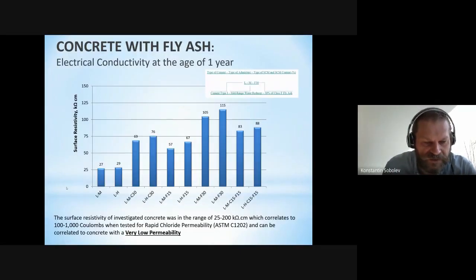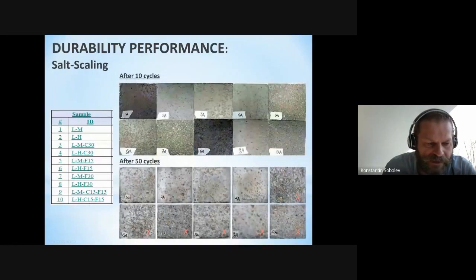The benefits of using Class F fly ash were in producing concrete with very low permeability. Most of these concrete types had very low permeability, but still the Class F fly ash based concrete had extremely low permeability. But what we've seen, and this is salt scaling, basically the effect of de-icing salts on the surface of concrete and accelerated erosion of concrete due to freezing and thawing. Usually the ASTM test constitutes 50 cycles. So if you look at concrete with Portland cement 1 and 2, those were really passing the tests.